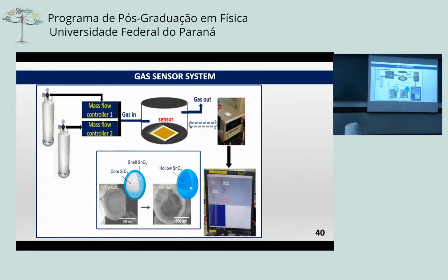So with this, we tried to look at their sensing behavior, but because it's carbon monoxide, we had to use a different setup, whereby we have the sensor here, the chamber, and we have mass flow controllers. One mass flow controller is for air, the other mass flow controller for carbon monoxide, and then to the LCR equipment to get the measurements.